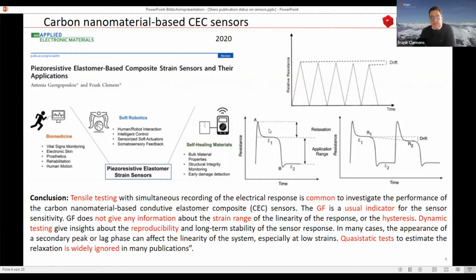is to use quasi-static experiments or quasi-static tests, where you again have a cycling process, but in between each cycle, at the top and at the bottom of the strain, you always keep a constant strain on the material for a certain time. And therefore what you can get out is, for example, the so-called relaxation effect. That means how much your resistivity or your conductivity changes with time. In this case, it is how much your resistance drops down. And this gives you a feeling for how reliable or how accurate your sensor is. So can you really use your sensor to detect different strains nicely?